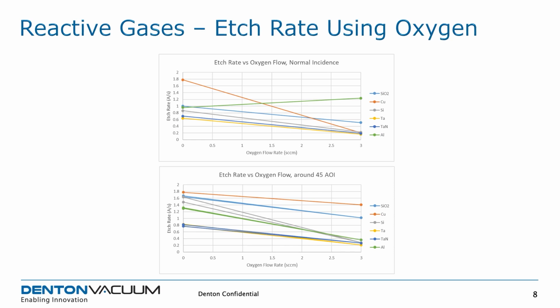Okay, so one of the reasons for introducing reactive gases is because you can often find an angle where 2 different materials have the same etch rate. But once you go to a more complex material system and you're trying to match 3 or more materials together, then there's a possibility of doing that by adding some additional gas.